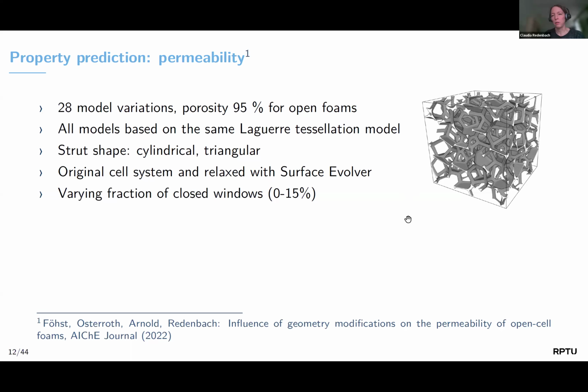In others, we actually do have rather irregular cell systems, then you rather use the Laguerre tessellation as is. And another thing that we did was we introduced these closed windows, the motivation basically being to provide some areas where the cells could settle down. And what we did was also vary the amount of such closed windows, trying to find some kind of compromise between high permeability, but then on the other hand, also surfaces to settle on.